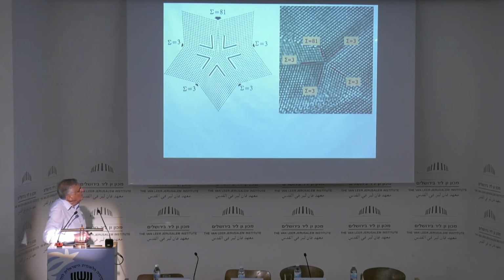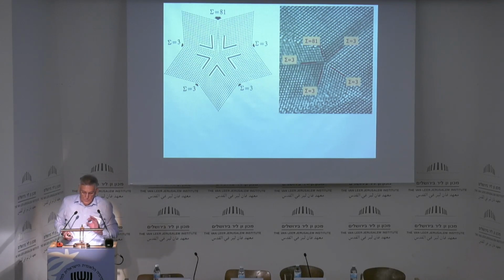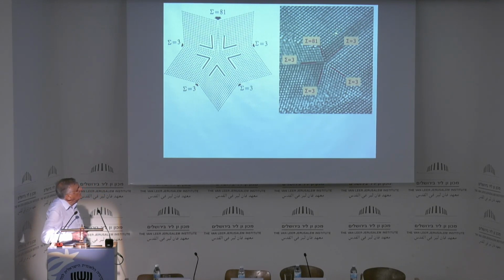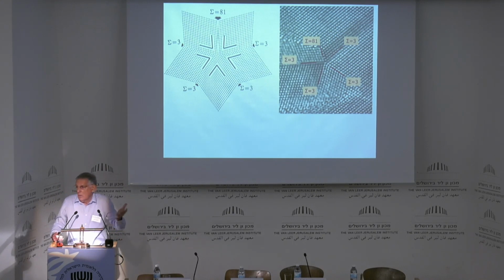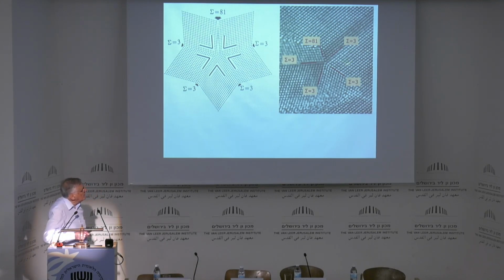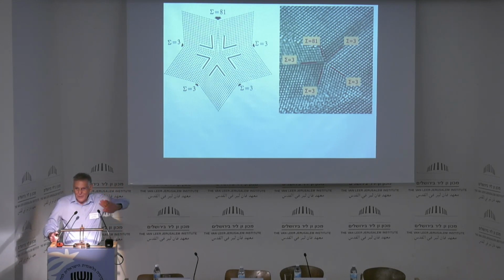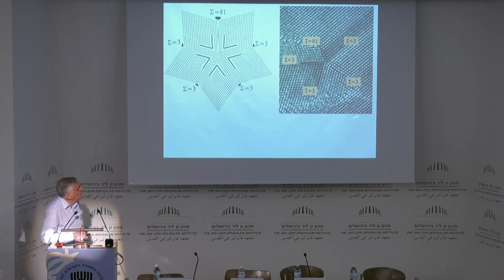It's a very special boundary, because it's like a mirror that reflects this plane onto here, and this onto here, and this here, and this there. So these are like mirror images. Now, why did I think that I have something like this? Because of the following. If you take a diffraction pattern for one of them, clearly you will have a periodic diffraction pattern, because it's a periodic structure. Nothing special. If you take a diffraction pattern from the other one, you will have the same diffraction pattern, but rotated 72 degrees. Why? 360 divided by 5. And so on and so forth. So this is rotated 72 degrees to this, 72 degrees, and so on.